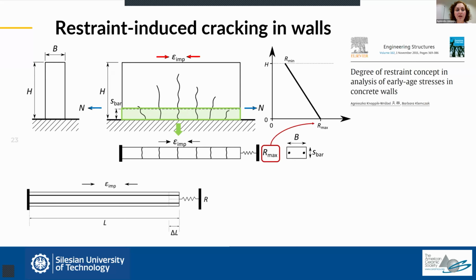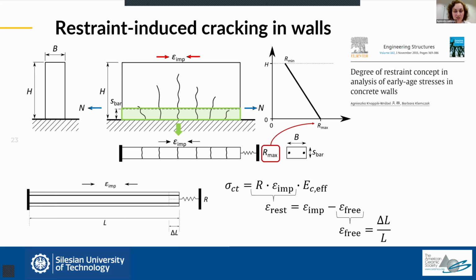We will have a tie which is symmetrically reinforced with a reinforcement that we would design in such an element. But we don't assume full fixation. We only use a certain level of restraint. Therefore, when such a tie experiences shrinkage or a potential shrinkage, some part of this shrinkage will happen. So we say that some part of this strain is a free strain. So we will have some level of deformability. However, the rest of this imposed deformation is restrained, and this restrained part of strain will cause the actual stress, which can be calculated using such a simple formula.